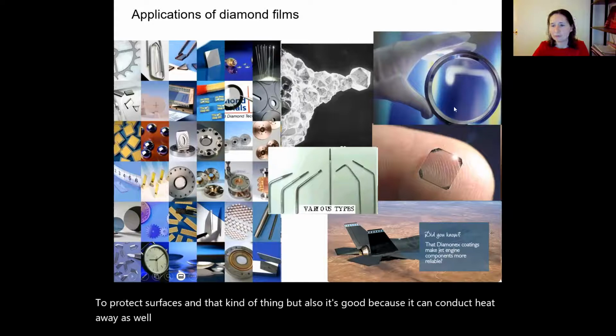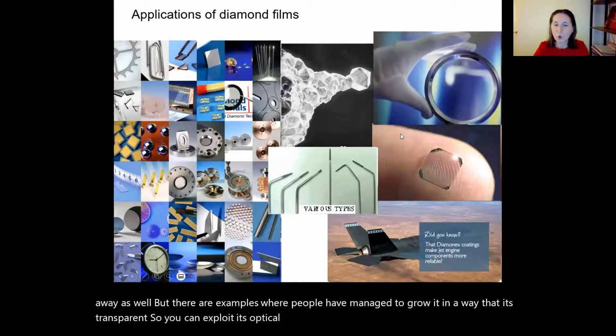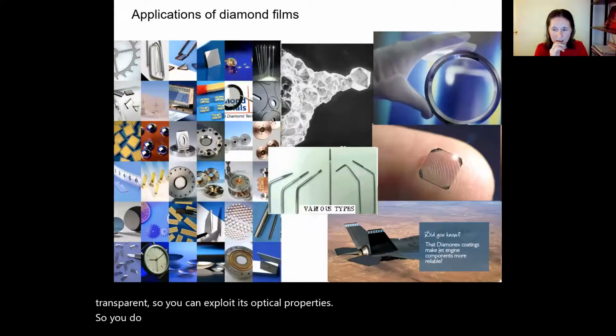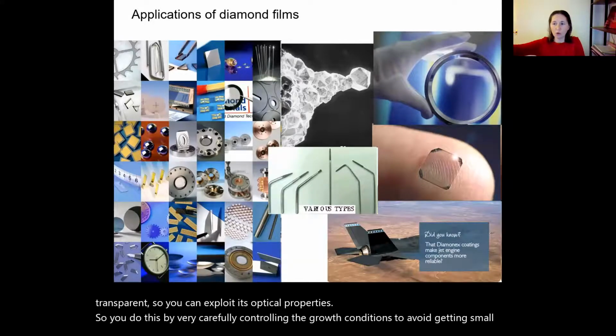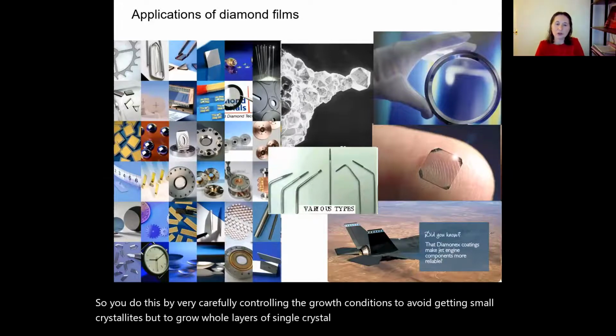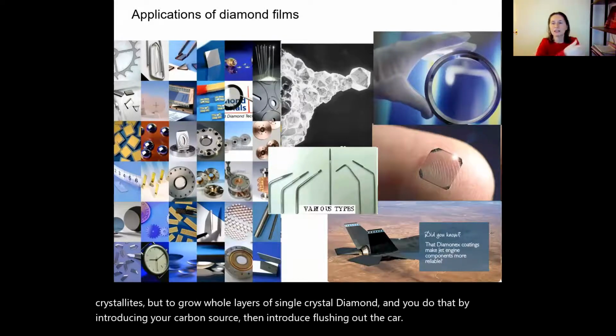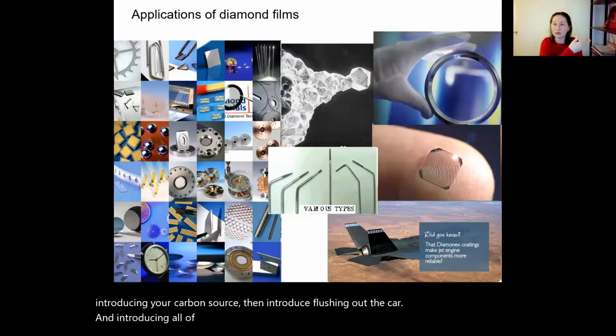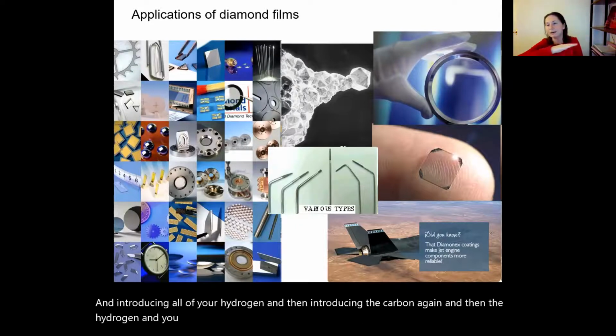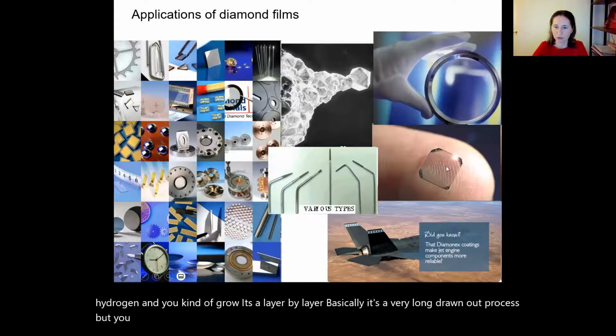But there are examples where people have managed to grow it in a way that it's transparent, so you can exploit its optical properties. You do this by very carefully controlling the growth conditions to avoid getting small crystallites, but to grow whole layers of single crystal diamond. You do that by introducing your carbon source, then flushing out the carbon and introducing the hydrogen, and then introducing the carbon again, and then the hydrogen, and you grow it layer by layer, basically. It's a very long, drawn out process, but you can then grow diamond with really high optical properties.